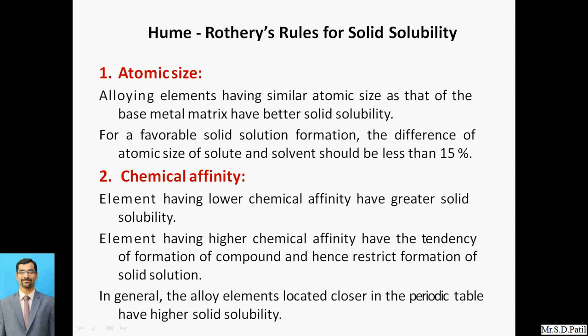So what is the chemical affinity? The element having lower chemical affinity has greater solid solubility. Whatever the elements may be, if it has lower chemical affinity, it has greater solid solubility. What is the meaning of chemical affinity? The element having higher chemical affinity has the tendency to form a compound and hence restricts the formation of solid solubility. So if chemical affinity is lower, then the solubility is greater.